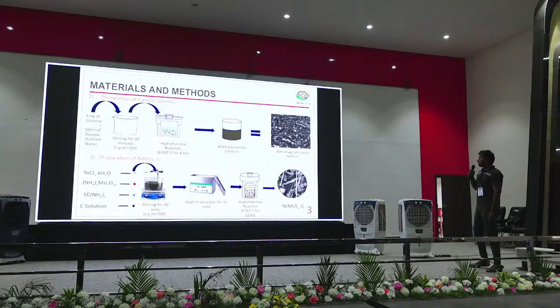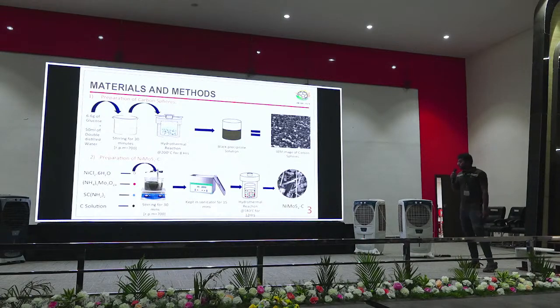Material and synthesis. I am going to prepare nickel molybdenum sulfide with carbon. This is a two-step hydrothermal method. First, carbon sphere was prepared from glucose. In the second step, the prepared carbon sphere was mixed with nickel chloride hexahydrate, ammonium molybdate, and thiourea.